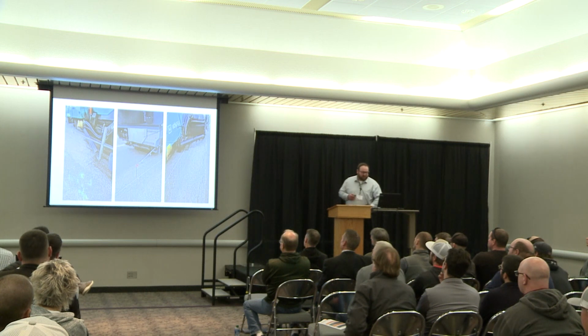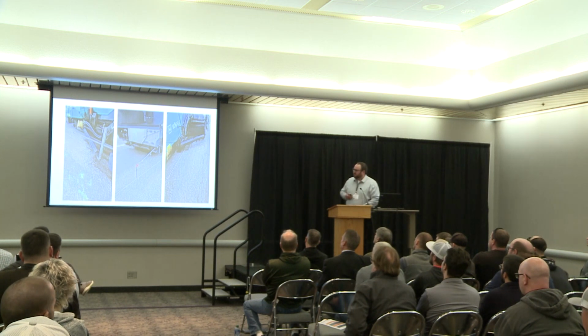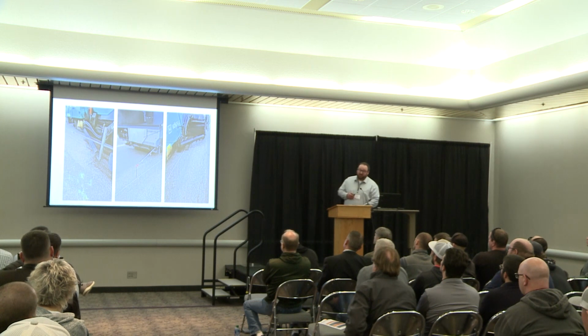So the spray paver was part of the SPs for both the thin lay and the ultra thin bonded wear course. They used a CRS2P oil. And I guess the nice thing about this, after being on projects in the past, using a spray paver, there was no wheel tracking for any of the dump trucks. You weren't stepping on tack if you were a ticket taker. I mean, no one was stepping on tack, so it was all there, just coming really clean. So I think that led to a really good bond with these preservation methods.